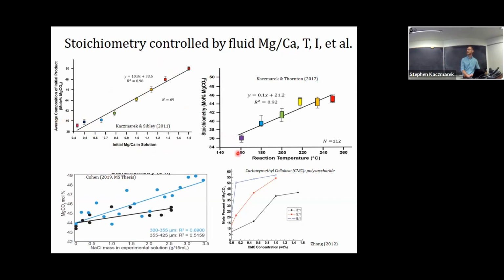Same goes for temperature. Increase the temperature, you increase the rate, and you increase the amount of magnesium. So you make a dolomite here at 160 with about 36 mole% magnesium in it, and you make one at 250 and it's about 46. So pretty big difference.